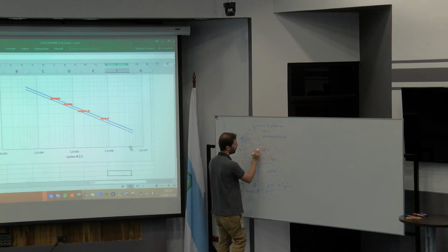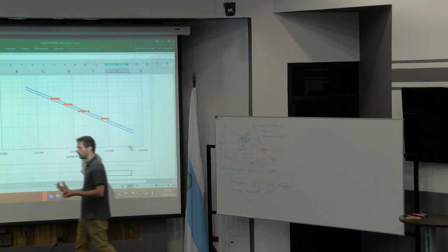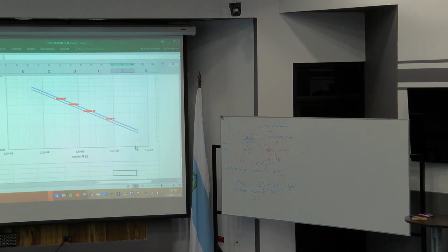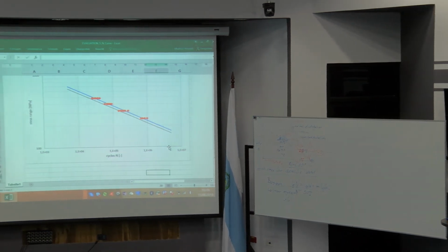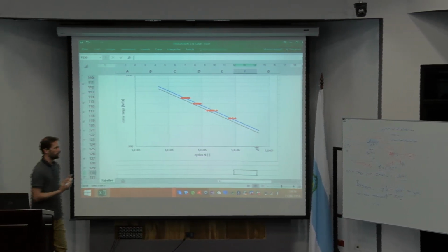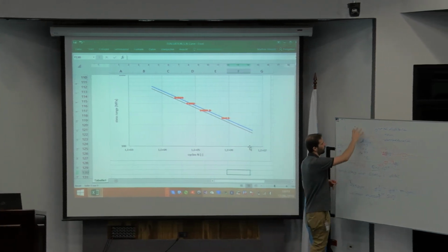And that's how, at the end, you can define also the curve with the horizontal plateau, just to get the information on where, or beyond which stress state, stress range, you don't have any failure in the material, theoretically. And so at the end, you have defined at this level the value for HCF and VHCF.